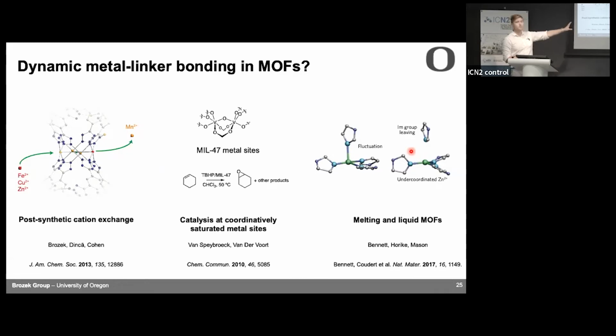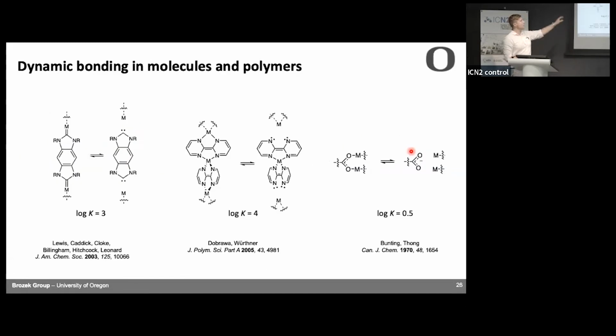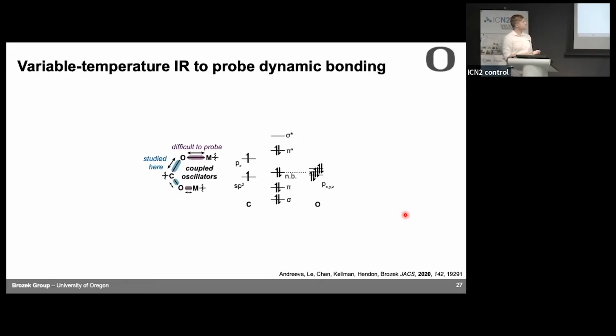And so that was the goal of my lab. Can we actually see the dynamic bonding? So this would be weird for the MOF community, but it's actually totally accepted in the polymer community, metal organic polymers. So for example, in metal carbene polymers and metal pyridyl polymers, this is so well established that people have actually measured the equilibrium constant. We know what fraction of the time the ligands are actually bound to the metals. And like I said, this is very well reported for molecular metal carboxylates. And those equilibrium constants are really small. So a log K of 0.5 would mean that about 30% of the time, there's not even a bond there. So imagine what that must mean for a MOF. So this is what we wanted to study.